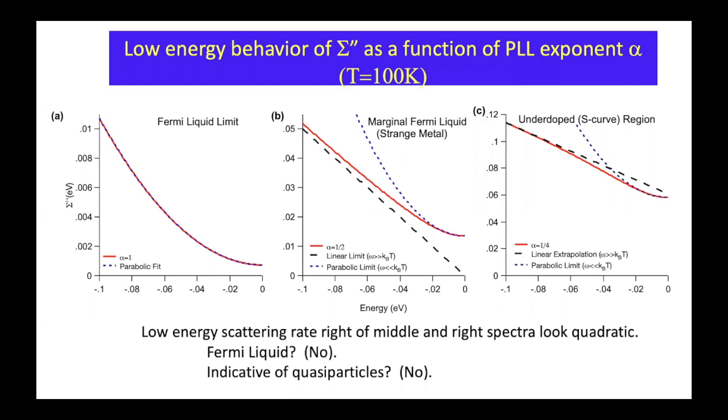And then there's the negative versus positive frequency side, and we're only probing the negative frequency, or the binding side. So we looked at symmetrized scattering rates, not the electronic structure, not the band dispersion. We can symmetrize the self energies. Sigma double prime should be even and sigma prime should be odd. And then put some canting one side versus the other, and look at a variety of possible cantings with basically similar form on both sides. We find we get the best results if it's symmetric. But this is all uncharted territory, so it's a great question. We don't have full control of the unoccupied side of it. But at zeroth order, we find the best result if they're symmetric.